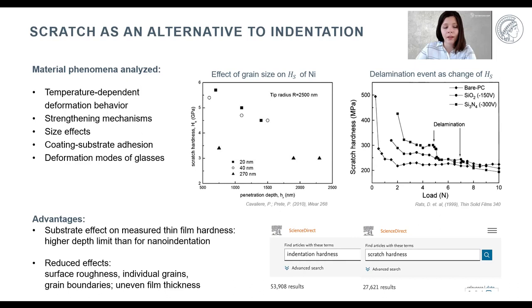In large part, this is due to the inability to draw a parallel between the hardness definitions in indentation and scratching. The indentation hardness definition assumes that there is no friction between the indenter and the surface, and on the other hand, the scratch hardness is rather strongly related to the shear stress at the interface. In a number of studies that tried to analyze the relation between indentation and scratch hardness, the results were quite different, and the hardness ratio varied from 0.4 to nearly 2, depending on the material and the tips used.